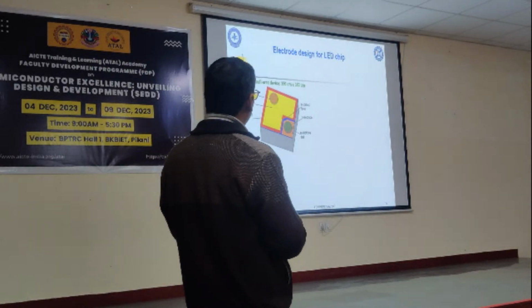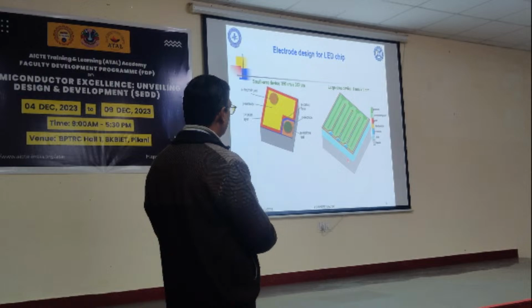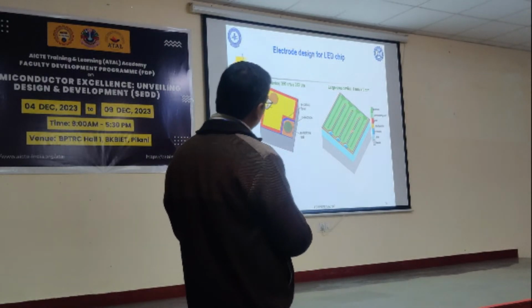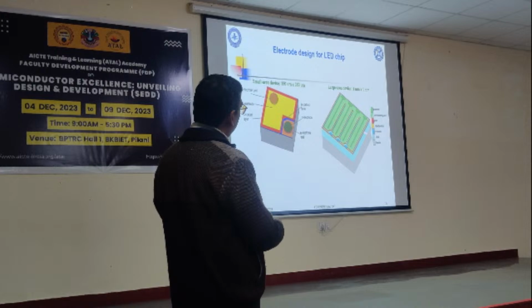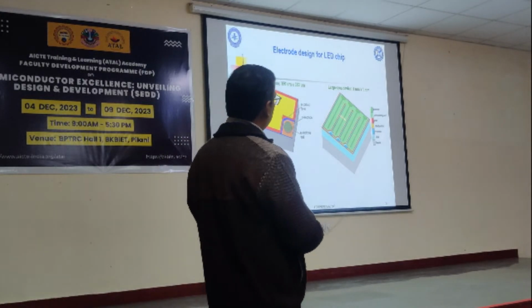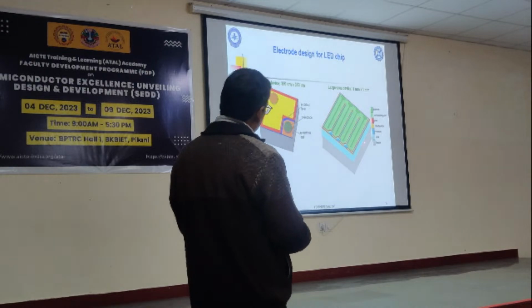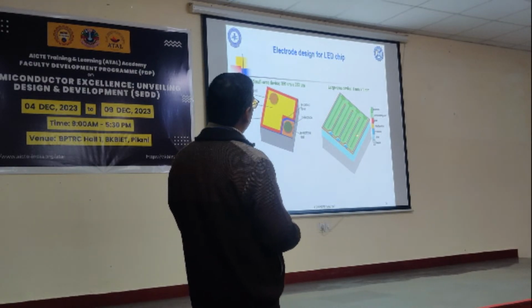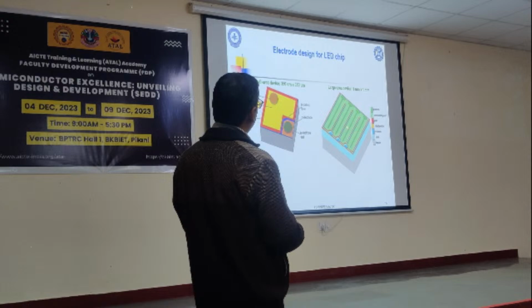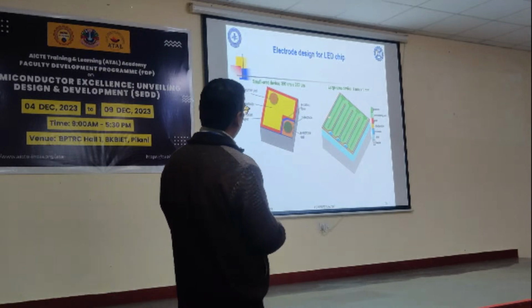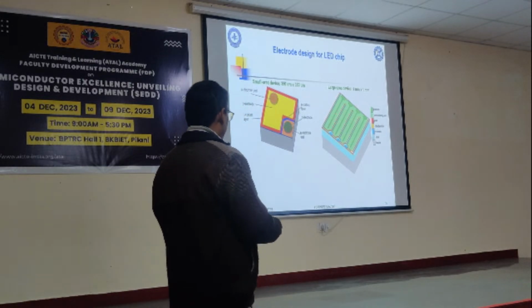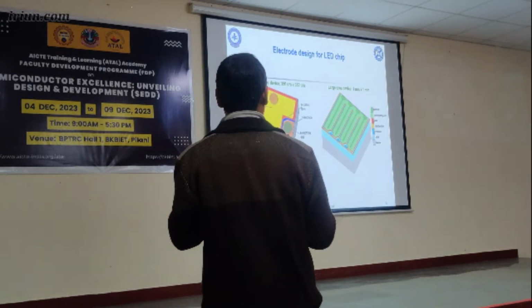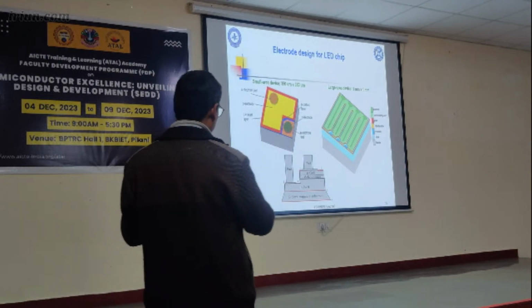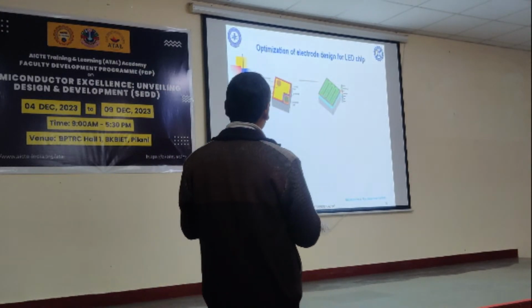So what we need to do is go for this type of finger structure. So here, a very thin layer of P and N interdigitated structure we can consider, so that the current is uniform within this emission. All this green area, the emission area, will be uniform, because the distance from P to N will not be that much, so that the current density will decrease. So we have to consider this type of structure. So this is the cross-sectional structure.